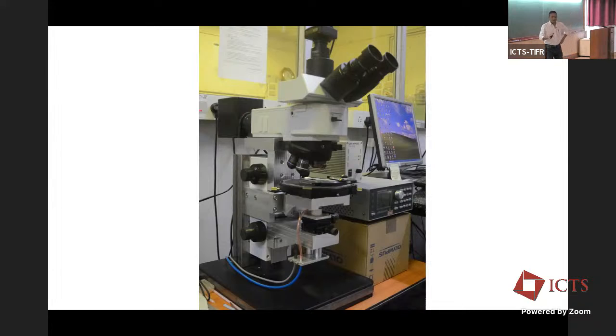At this point of time, if you aim for say 1 degree misorientation, it can easily be something around 1.2 or 1 or 0.8 or something of that sort. But now we have techniques in which we have stabilizing layers of some form, so that can give you better accuracy. When we make it, we do it purely mechanically, but then we characterize them using transport. So the yield, I would say, is about 20 to 30% of what you want and what comes out.